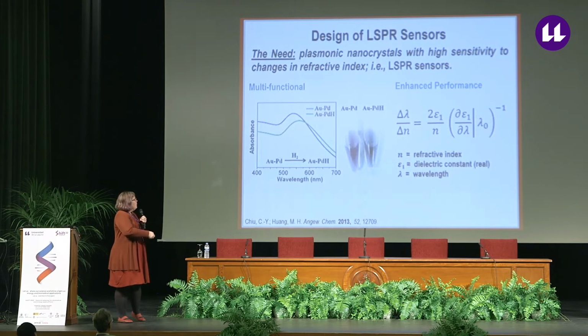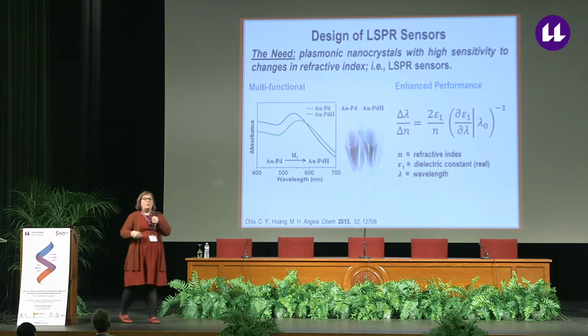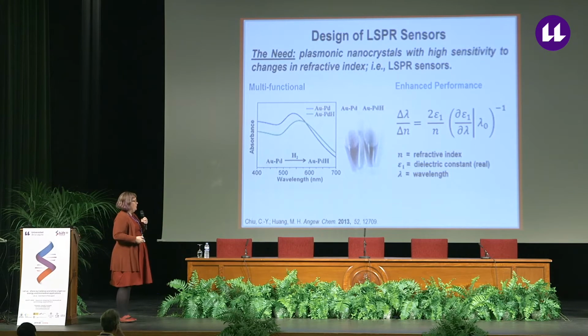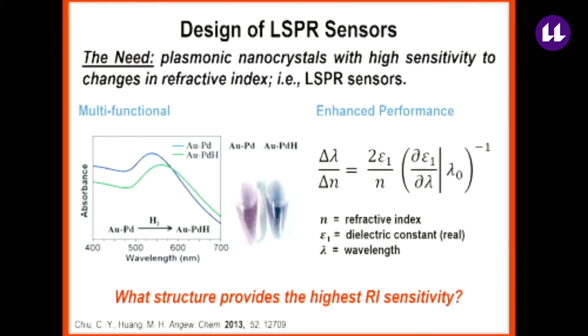But what I got particularly interested in was this idea of enhanced performance, and it turns out that when you look at the dielectric functions of palladium, gold, silver, some of the common plasmonic materials, palladium actually has a low dielectric dispersion through much of the visible and near infrared, the regions that we're most interested in. And this could bring a boost in this sensitivity term. But we can make a whole lot of different bimetallic nanocrystals, and so a question then becomes, what type of structure provides the highest sensitivity to changes in local environment?